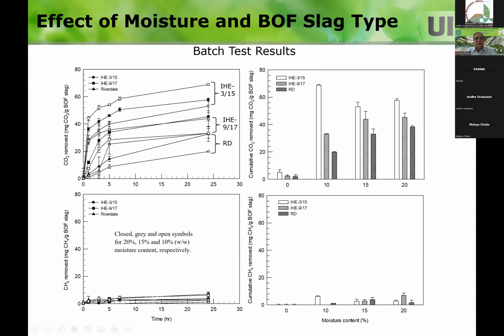One thing that is highly revealing here is, if the slag is very dry, you will not get any sequestration. But if you have 10%, 15%, 20%, you need to have some moisture. With the 10% moisture content, this slag had very high carbon sequestration. Each one has a high amount of sequestration, but you need to have the moisture. Nothing happens to the methane, so mostly the CO2 is going to be sequestered. Even if you put a gas source that has methane and CO2, the CO2 is the one that is going to be sequestered.